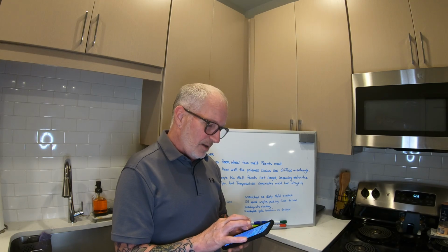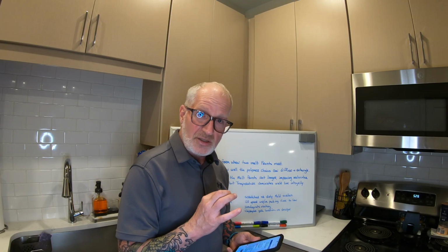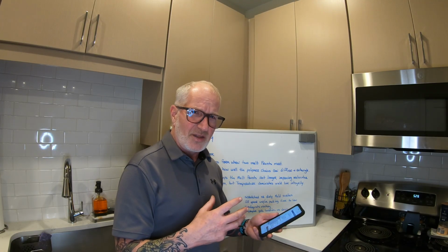Now the last one is for the mold. Increase mold temperature, clean vents, add or enlarge. Okay, increase gate size or runner size, introduce cold slug pockets, or change gate location. So think about that when you're thinking of the 3 M's.